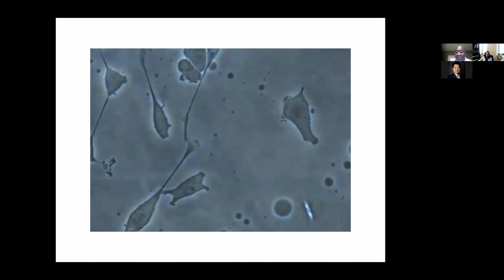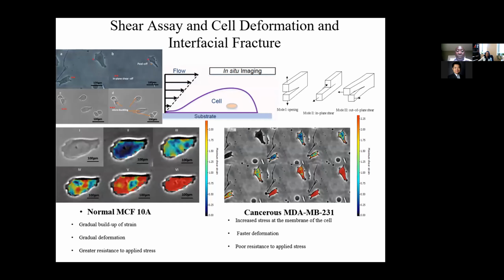So from experiments like this, what one can then do is, by doing displacement mapping using digital image correlation, you can actually see how we start shearing the cells and inducing strains that are both axial tensile and axial compressive. And so with these kinds of strain distributions, it's not surprising that as you increase your loading of the cells, you deform them more. And if you look at the top left, you'll see evidence in some cases of micro-buckling in segments where you have local compressive strains, and then axial deformation in regions where you don't.